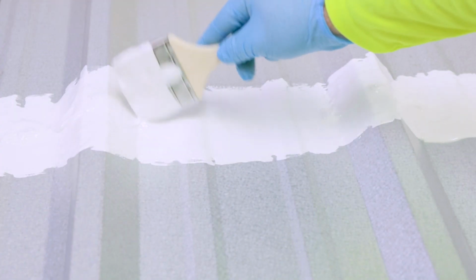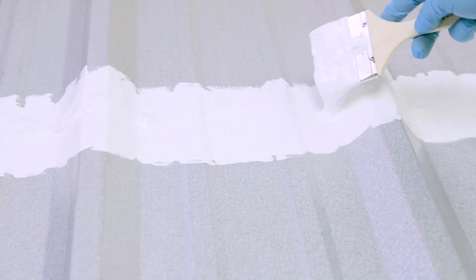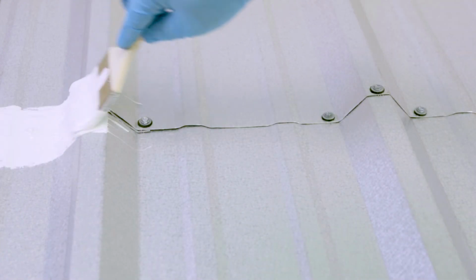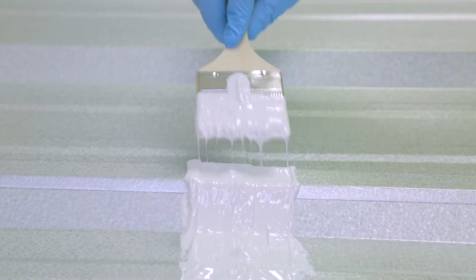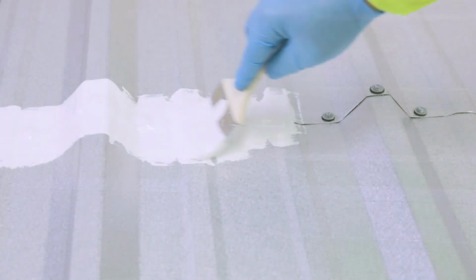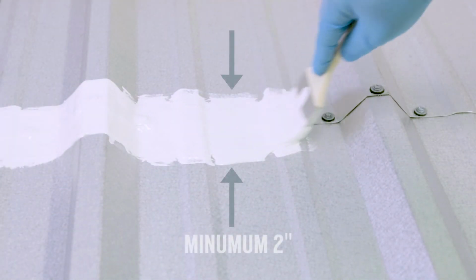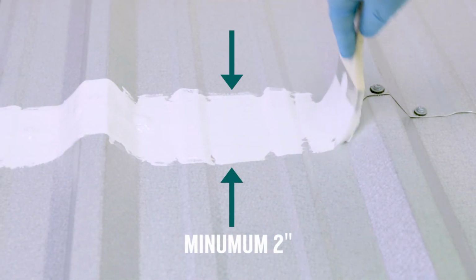Apply an additional dab of product over screw heads for complete encapsulation. Apply 2 coats of Polybright 77 Premium SEBS cement at horizontal seam at a minimum of 2 inches on each side at a rate of 3 gallons per square, which will give you 24 dry mils for each coat. Allow Polybright 77 Premium SEBS cement to cure prior to overcoating with acrylic surface coating. Silicone is not compatible with this product.